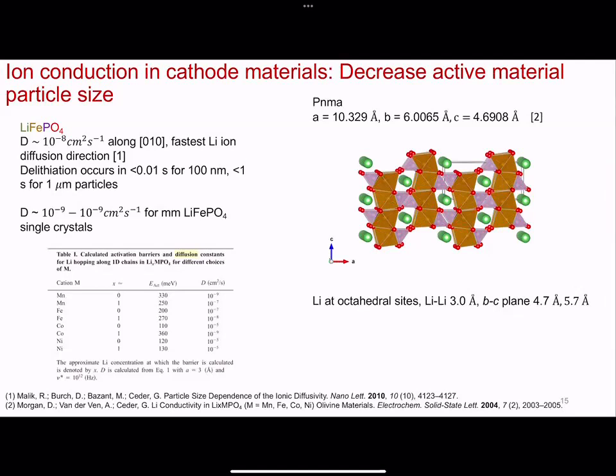And so if that's the case, lithium ions need a whole channel to move in and out. So they need the whole channel to diffuse. But if there's a blockage, now your fast ion channel is blocked. So the ion has to move to another site. That's a higher energy barrier. But if it's available, it will do it, statistically speaking. So if it can make that jump, it will, and it does. But it's going to come at a cost, right? It's higher energetically. So it's going to want to try to diffuse in the direction that's the fastest and lowest energy barrier, which is the 010 direction.